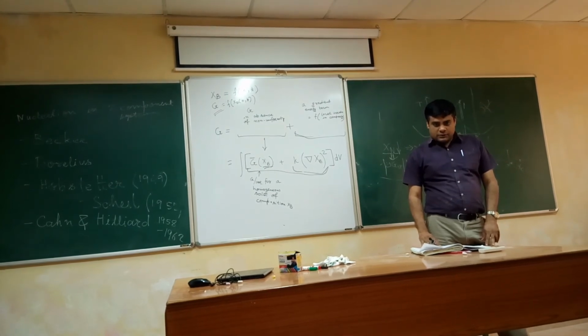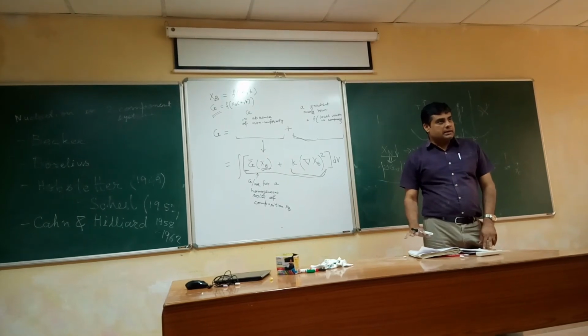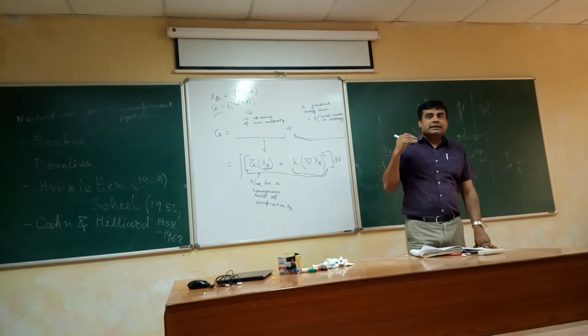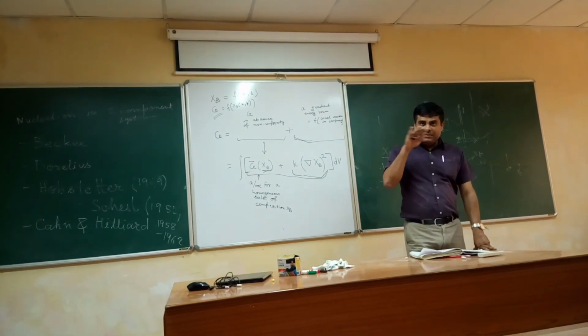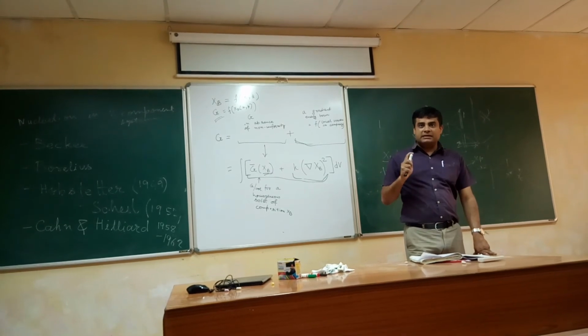And through mathematical derivations, they showed that as the temperature approaches the equilibrium transformation temperature, it behaves like classical nucleation theory.